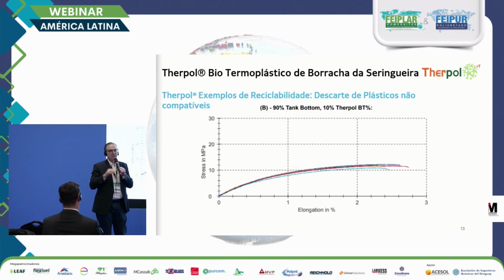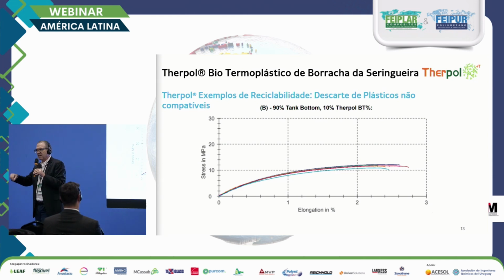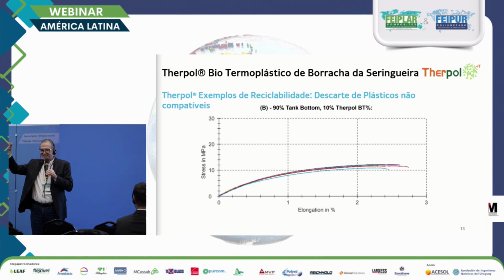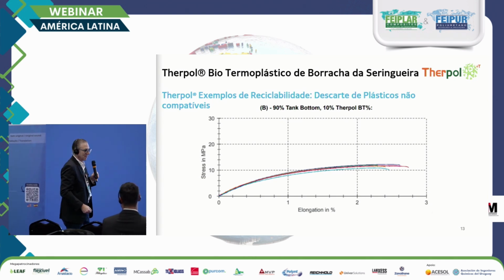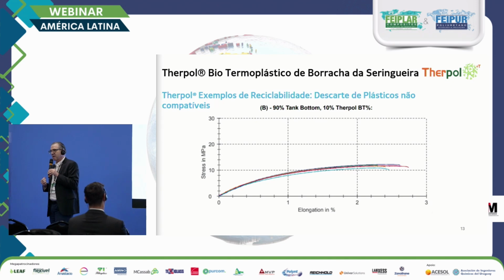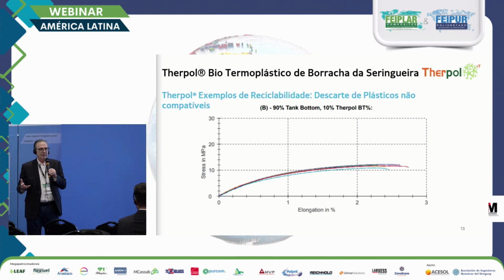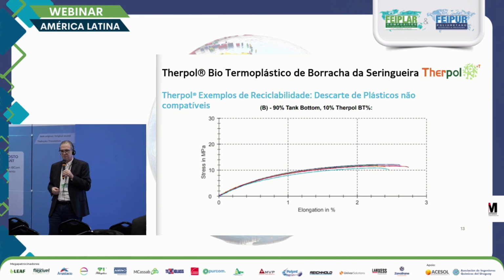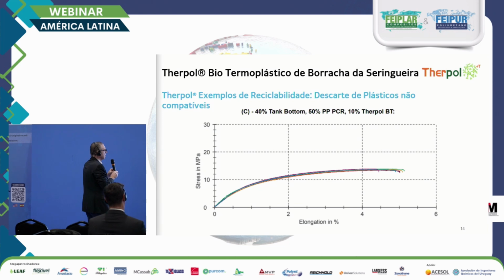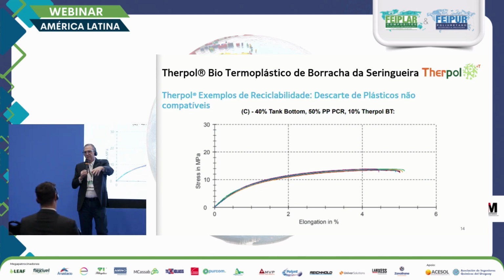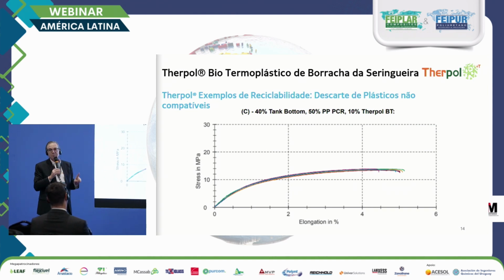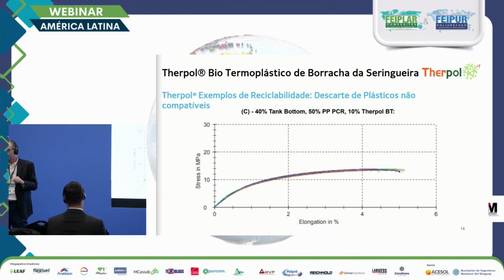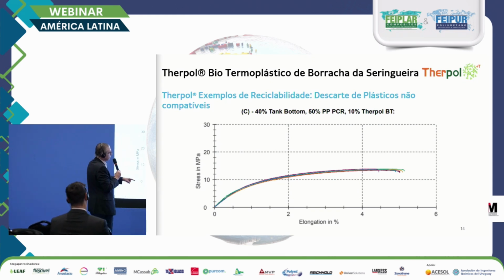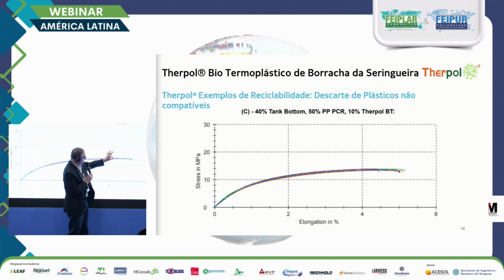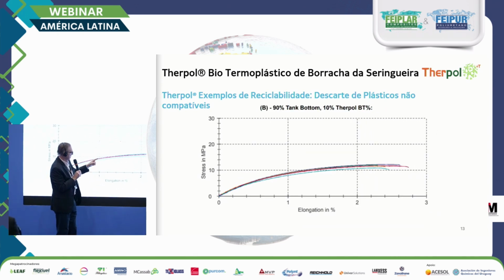Then we said, well, this isn't enough. And remember, circular economy, recycling, and all that is only valid if you have money, if you have some kind of financial results. So we discovered that Therpol with recycled polypropylene improves the properties of the recycled material. So we combined 40% of the tank bottom, 50% of recycled PP, with 10% of Therpol. And this is what we achieved. And you can notice that it's very stable results. But look at what we achieved. Can you go back to the previous one?